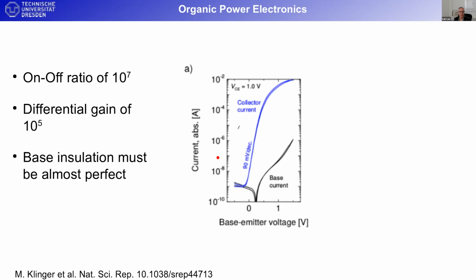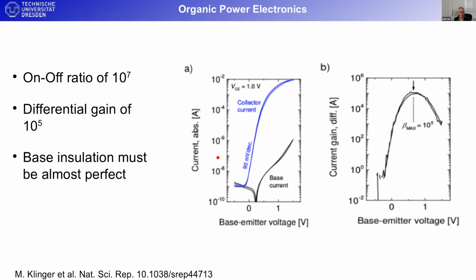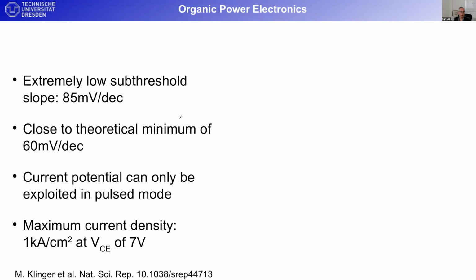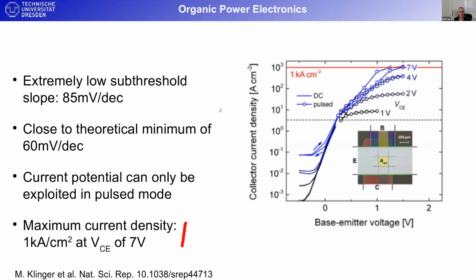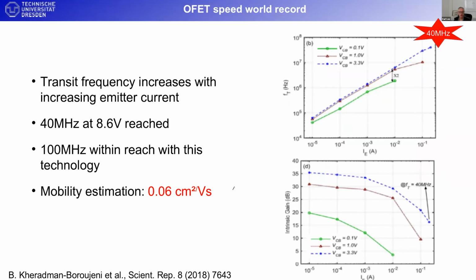And these devices are now exceptionally well operating. We have on-off ratios of 10 to the 7. We have differential gains of 10 to the 5, which means that the base insulation is almost perfect. There are no electrons entering the base anymore. They all go the way they should to the collector. And in terms of subthreshold slope, we are close to theory, and we have achieved very encouraging current densities. In pulse operation, these devices with a few volts work at a kiloamps per square centimeter, which means that you can, for instance, drive a high brightness OLED display with a very, very small transistor. And with these devices, we've now achieved speeds which are already 40 megahertz, and this at quite low mobility of 0.06. This can be increased by a factor of 100, and we expect that this can be scaled much further.